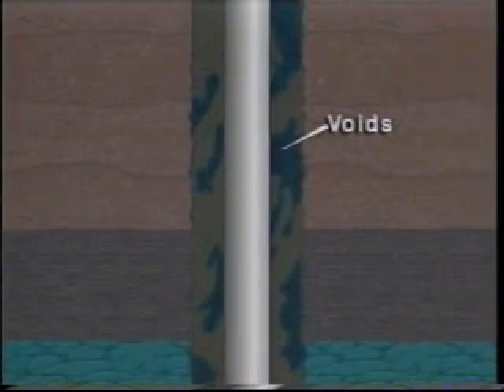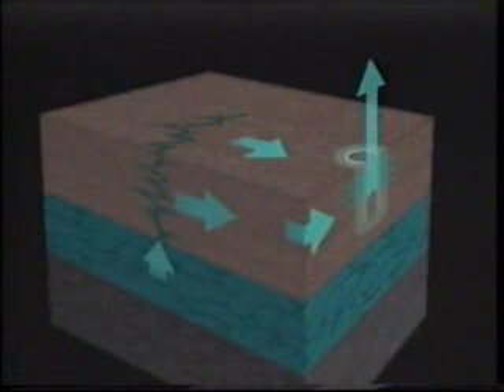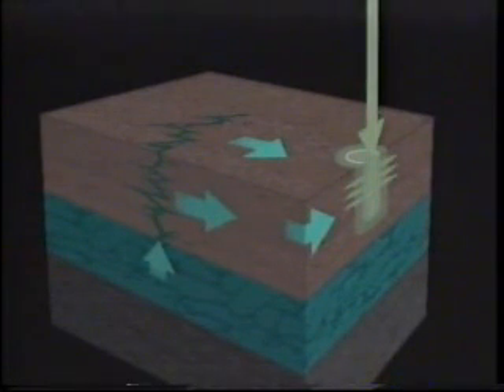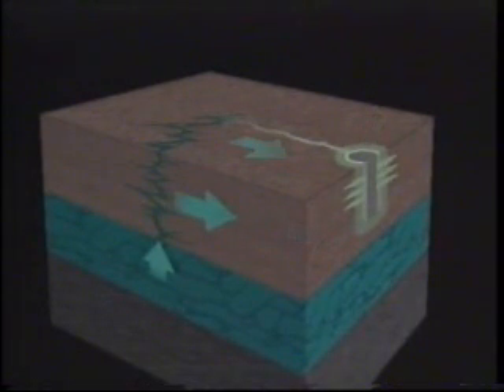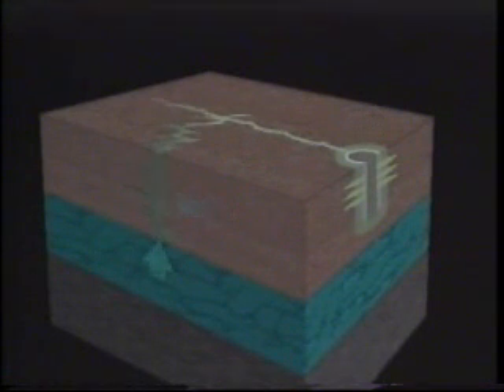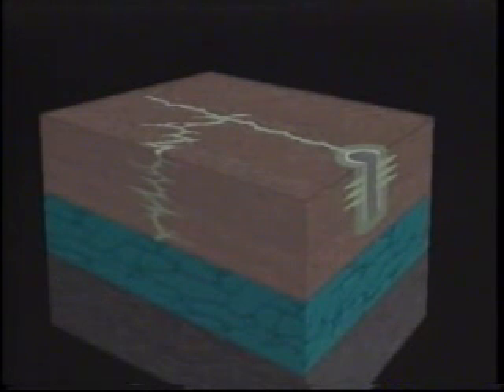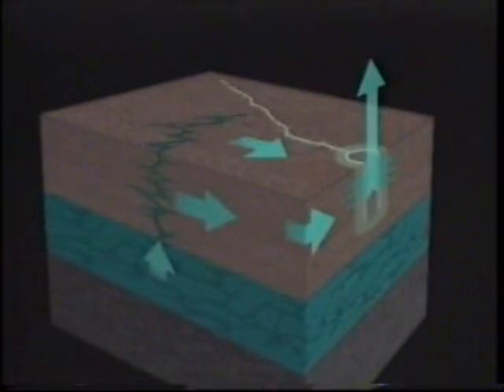Squeeze cementing is performed either to correct a poor primary cementing job or to stop unwanted fluid production caused by changing reservoir saturations or unsuccessful completion attempts. In a high-pressure squeeze, cement is pumped into the well at pressures that exceed the formation fracture pressure. This causes fractures to propagate from the well bore. These induced fractures are intended to intersect the existing fractures or voids responsible for unwanted production. The induced fractures remain full of cement after the treatment and thus block production from these areas. In practice, this method has a low success rate, probably due to the unpredictable growth of the induced fractures.